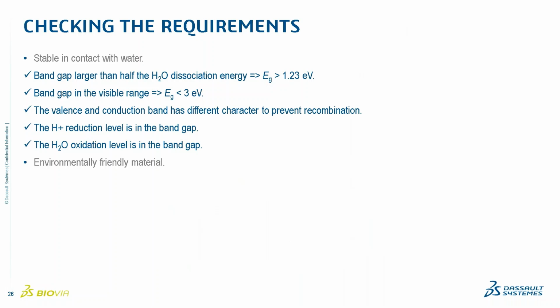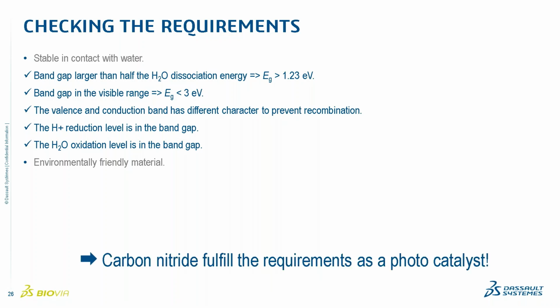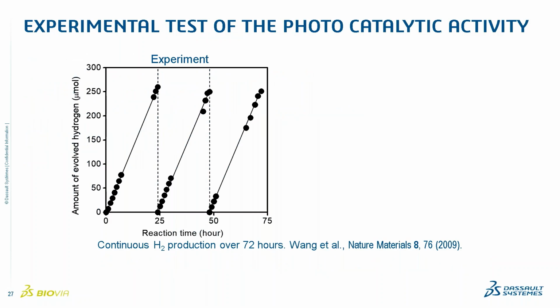So now we can check these requirements that we were formulating at the start, and we can see that this material, carbon nitride, does fulfill all the requirements that we can put on a photocatalyst. So it means that we now can make an experimental verification, and that shows that we have a continuous production of hydrogen gas from water.